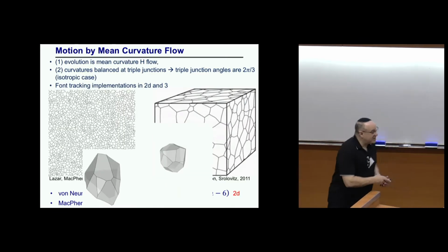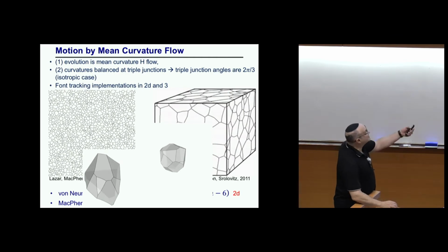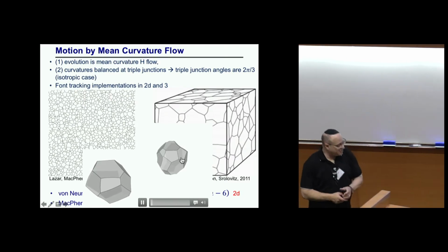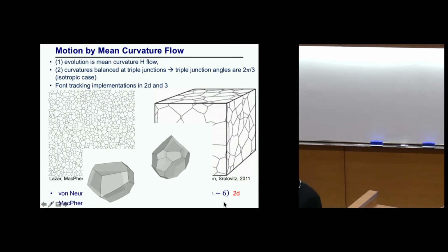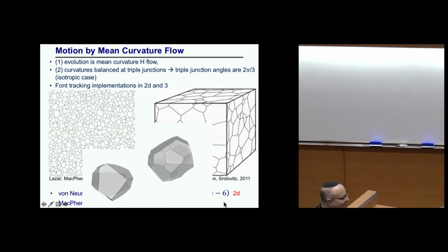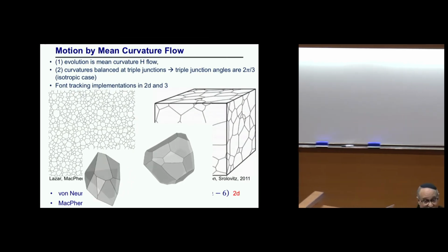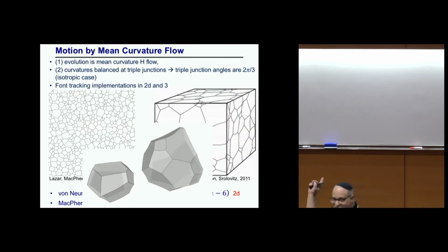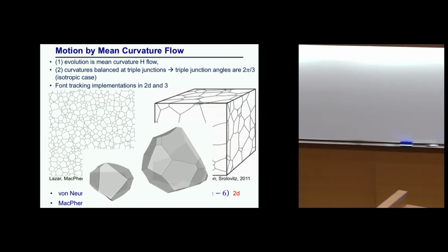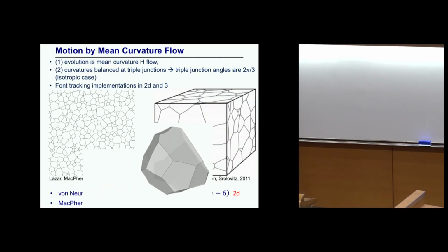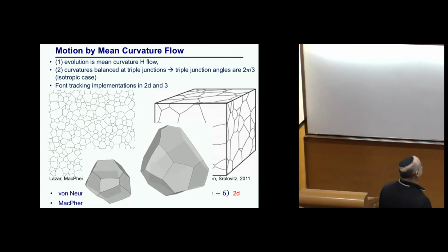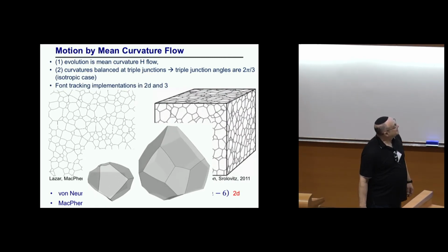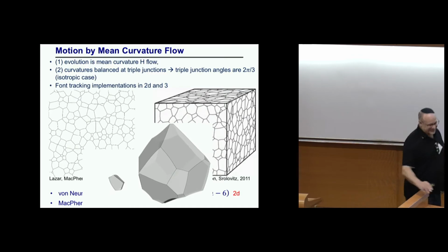And what I'm showing you here are just 2 grains plucked from the interior of that one, because what I want to do is make the following point. Those relationships that I just showed you about how the area or the volume of each grain evolves work perfectly well until you get a change in topology. And as you can see, topological changes happen all the time. So that's a really important thing, is you've got to be able to describe the topology part of this. You could sit here and watch this all day. Okay.